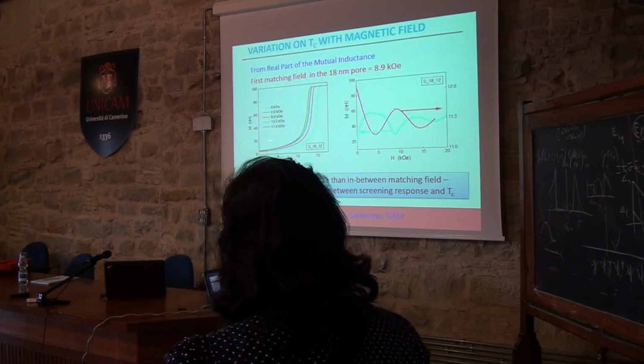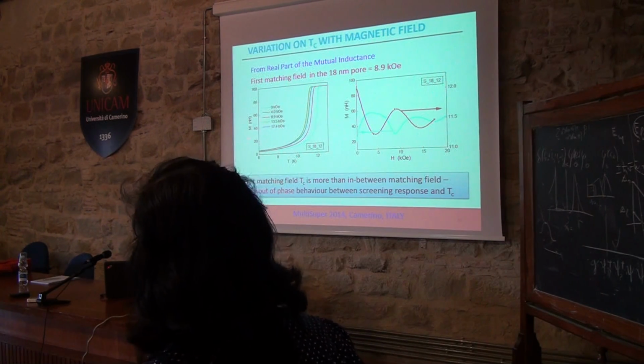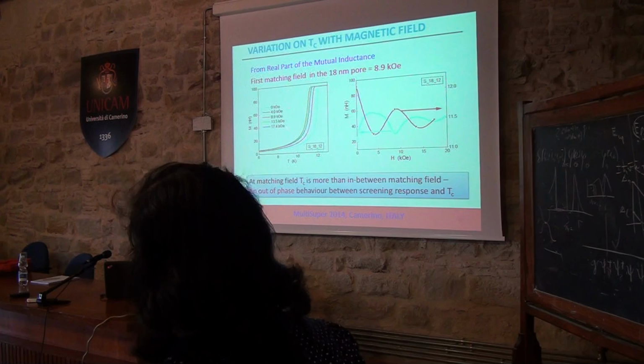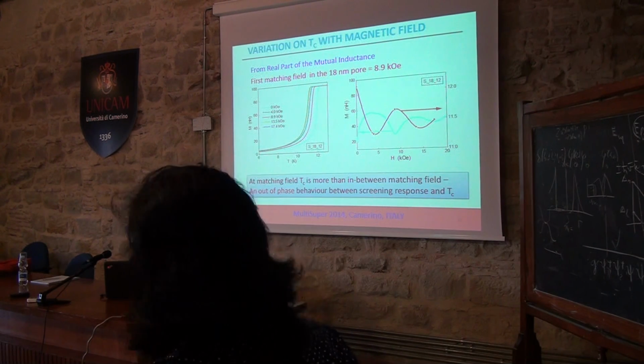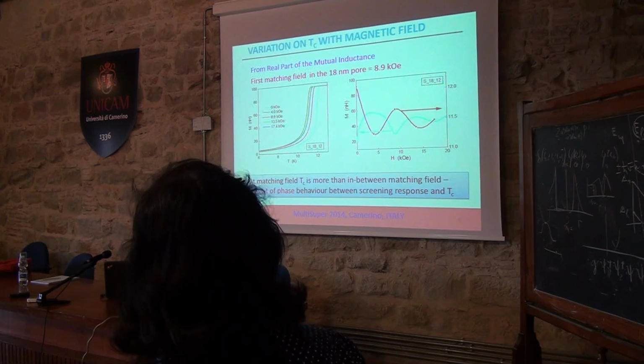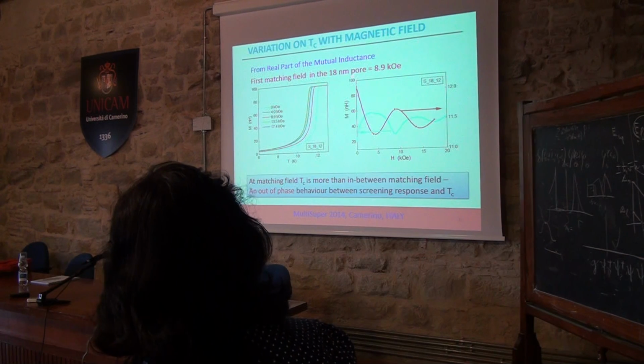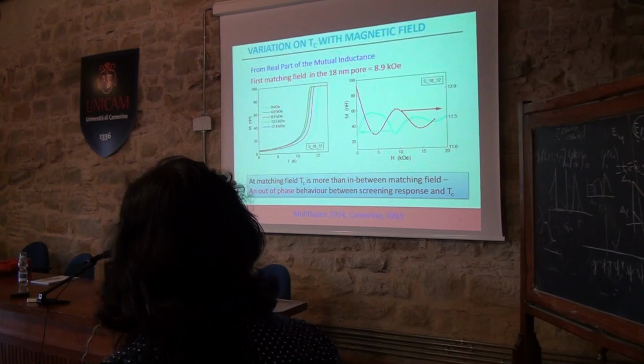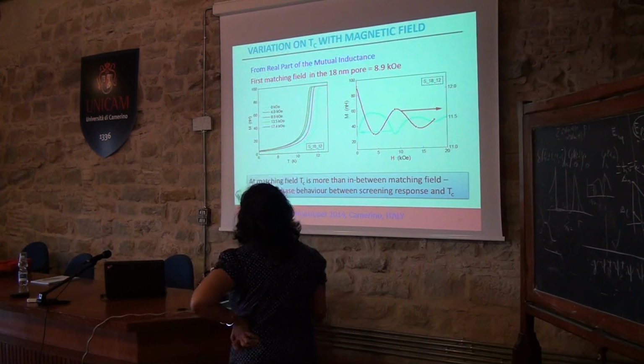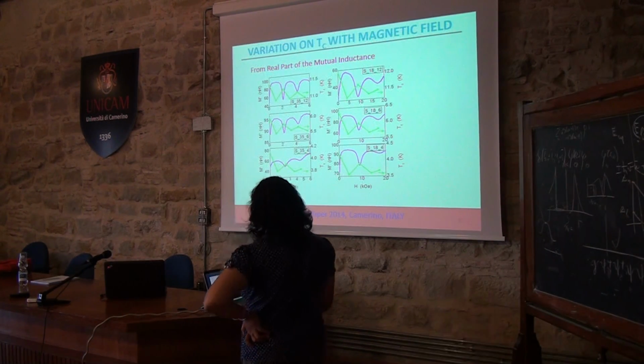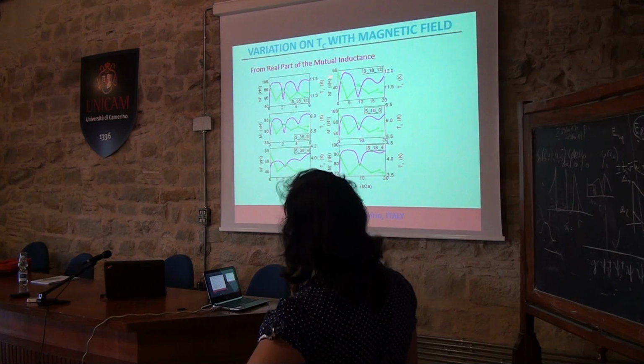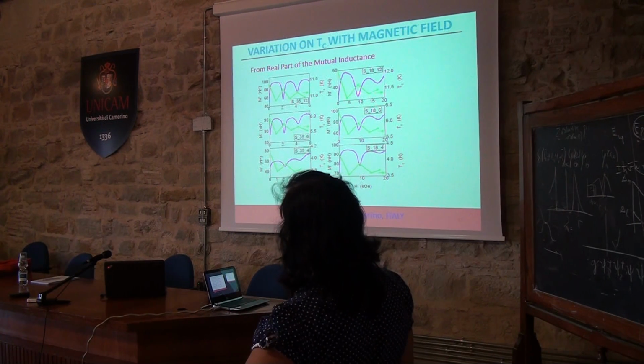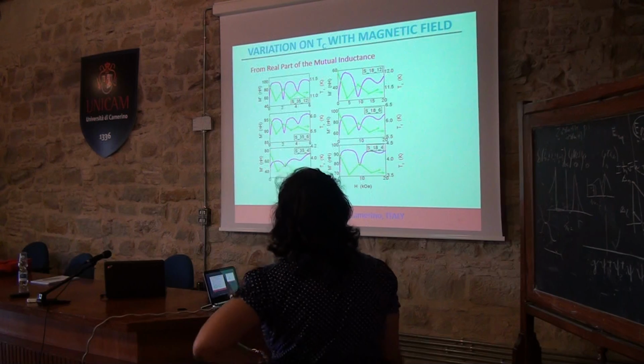What we did is that we measured the temperature dependence of the mutual inductance at different magnetic fields to find out the Tc. So we could get the Tc from here. And here you see that you start seeing the oscillations in Tc. This is the red curve over here. And you see it in all our samples. These green curves over here show the oscillation in Tc which we observe for all our samples.